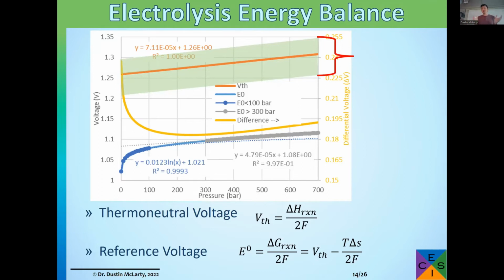Now there's always going to be some natural heat loss. So your actual operating thermoneutral voltage is usually a bit above this line just because you have heat loss. Surrounding that orange line is a green band, and this is representing your viable, sustainable temperature window. So you have fluids flowing through your stack, and they can come in a little bit below your operating temperature and leave a little bit above your operating temperature. So you might be able to tolerate up to 100 degrees difference between the inlet and outlet. And that thermal capacitance gives you a little flexibility in how you operate your system.